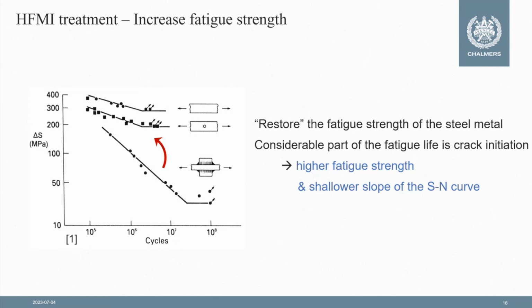So we have a higher fatigue strength, and more importantly, actually, we have even a shallower slope of the SN curve, because we are again reintroducing the crack initiation phase into the fatigue resistance of the welded detail.